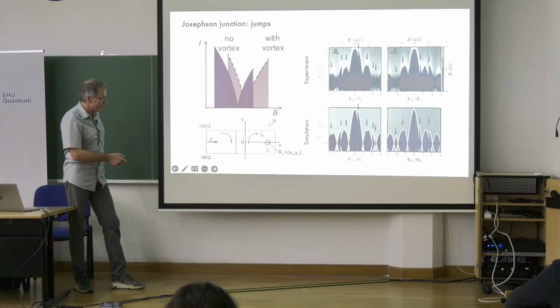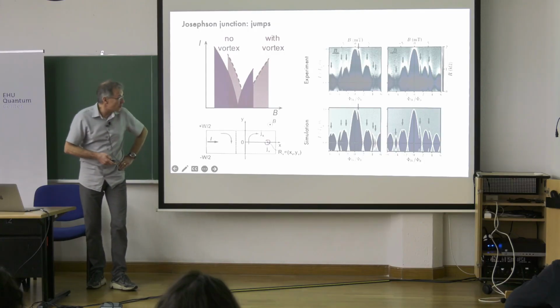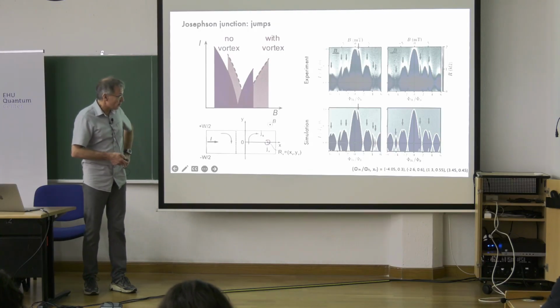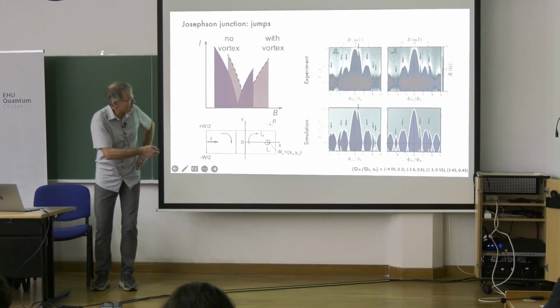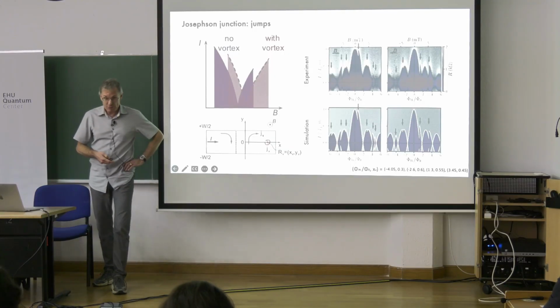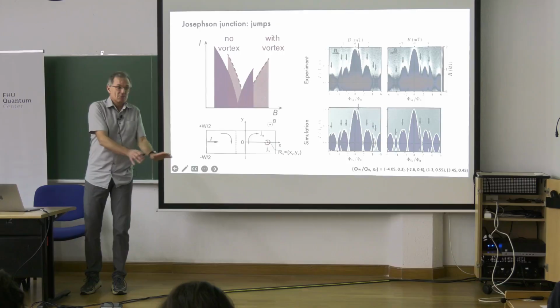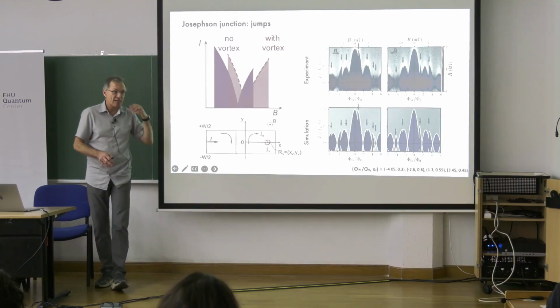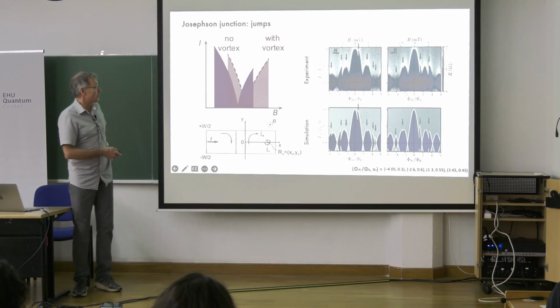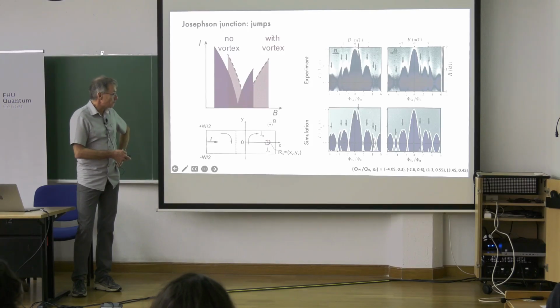Then this Meissner current reduces the current produced by the field, which is equivalent to shifting this Fraunhofer pattern to the right. And that's the theoretical plot when we place vortices here, this and this in this position, which looks pretty similar to what they observe in the experiment. Of course, we don't know whether what they measure is vortices or not. That's our interpretation. But that fits rather well.